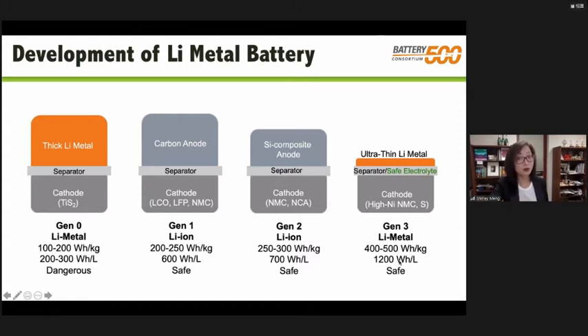So today, when we build the third generation, or second generation, lithium metal cells, you can see that we can afford to put a very thin layer of lithium metal, because the new electrolyte discovered by Pacific Northwest National Lab enables us to deposit and strip lithium with very high efficiency. So in theory, you can have anode free. But of course, anode free has other problems. I will just say we need ultra thin lithium metal, because most of the lithium will be contained in the NMC side.